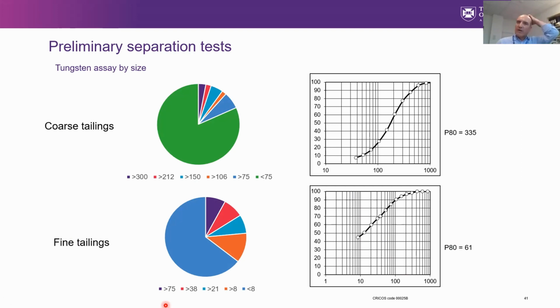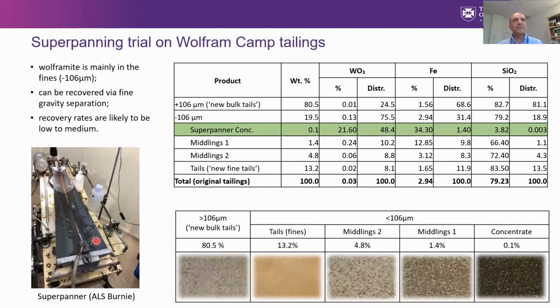Okay. So we also did some physical separation tests. This is a tungsten assay by size, and most of the tungsten is accumulated in the fine fraction. And so we ran what they call super panning, which is a gravity separation method. We created a concentrate from the finer fraction of the tail, which has about 22% tungsten oxide. So these images at the bottom show we have coarse material, sandy material with a lot of quartz in it,